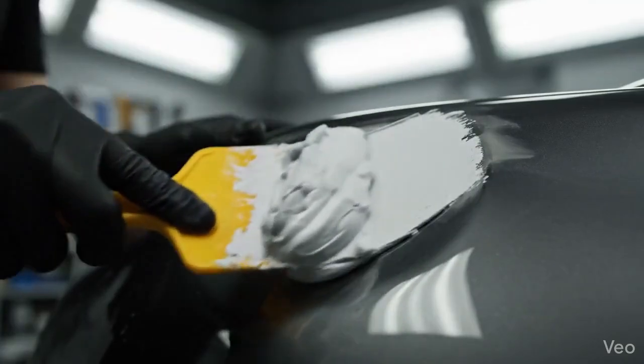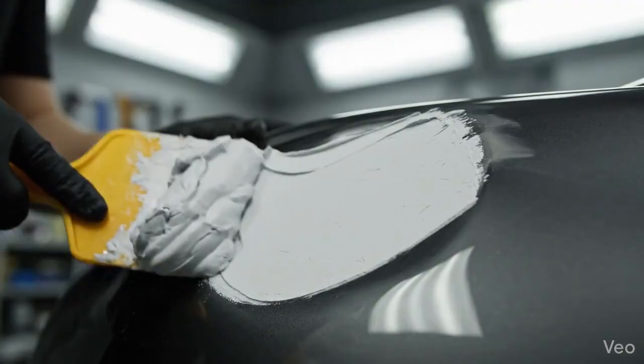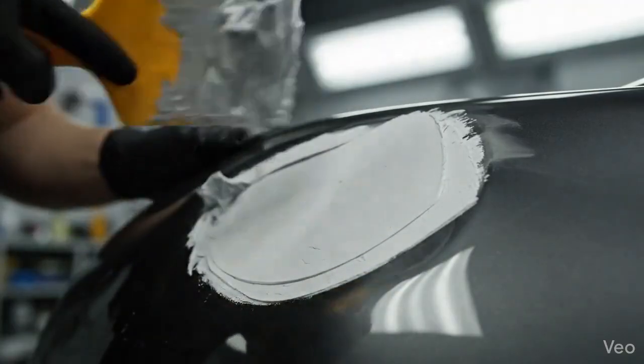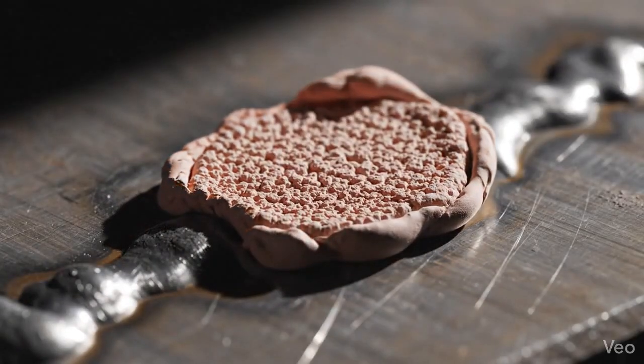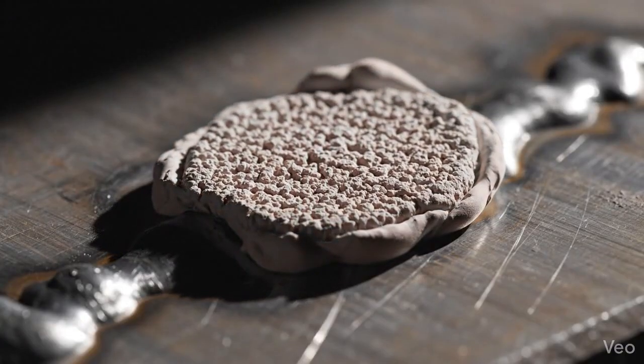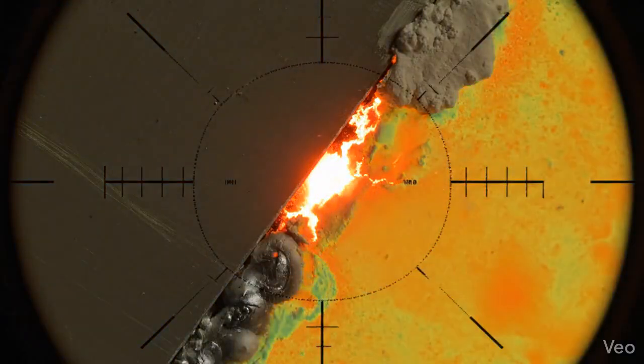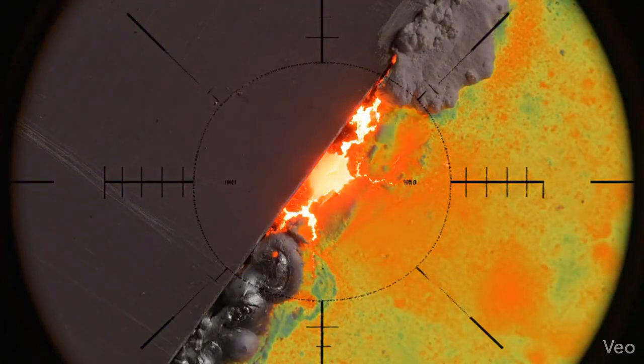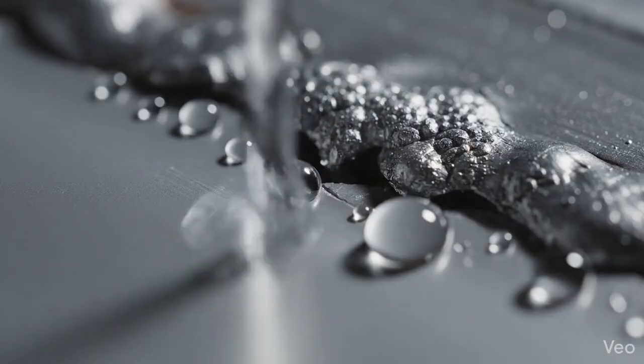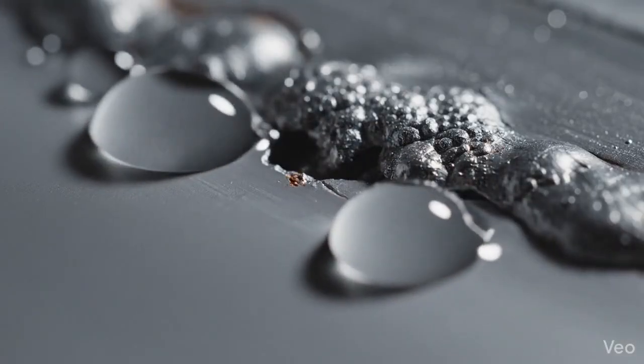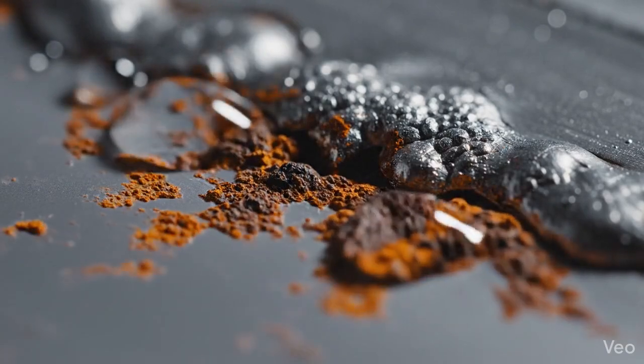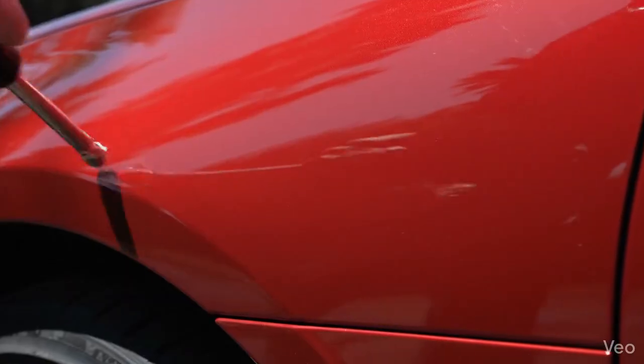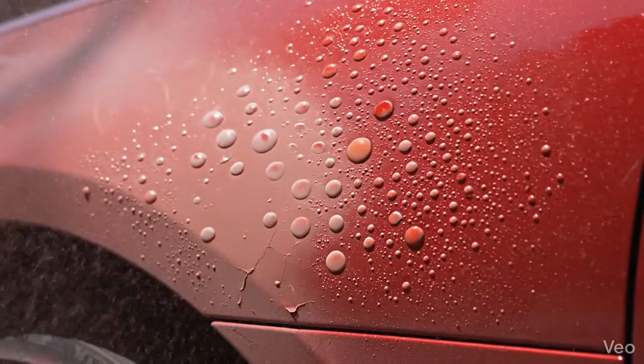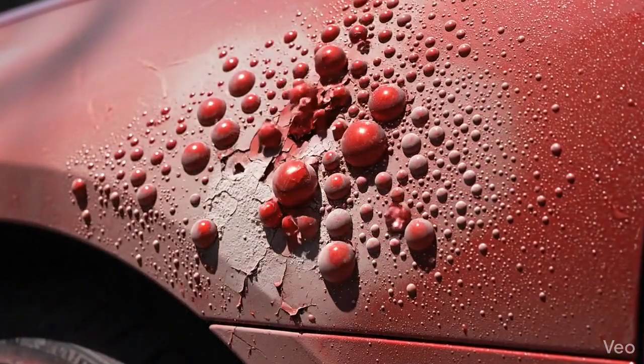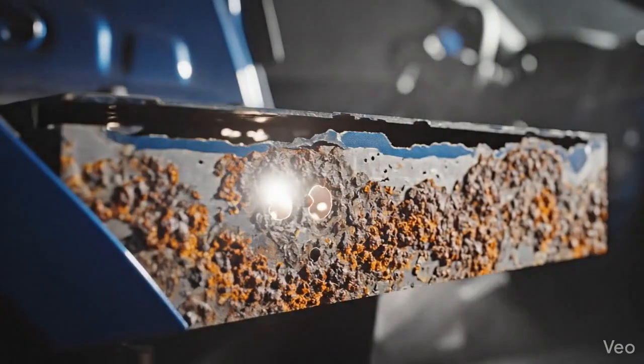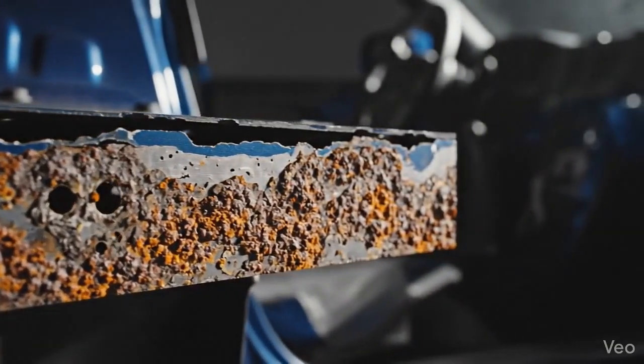Standard polyester body filler, the product most people associate with collision repair since the 1960s, bonds to the outer surface of the steel through mechanical adhesion. It cures to a rigid mass that expands and contracts at a different rate than the underlying metal as temperatures change through the seasons and through daily heat cycles. This differential movement eventually opens microscopic gaps at the bond line. Moisture finds those gaps. Rust begins beneath the filler layer. A blister appears years later, sometimes a decade later, sometimes two, and by the time it is visible from outside, the damage underneath is already extensive, and the repair footprint is larger than what you started with.